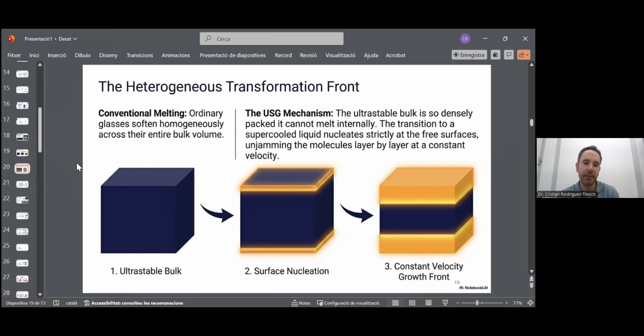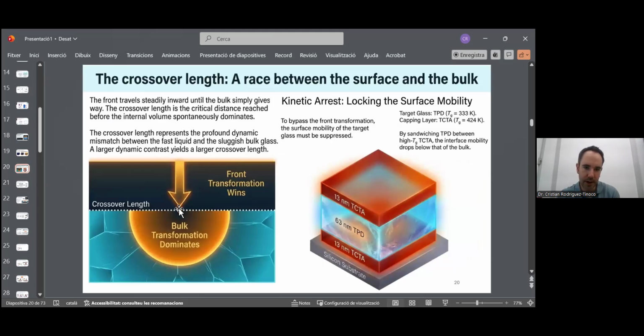What I want to say is that this front, so the liquid layer starts here on the surface and propagates into the bulk, but eventually the bulk of the system will go into the liquid state as well. After some time, the mobility of the bulk has had some time, and then it will transform into the liquid state. So we can define a crossover length, which is the distance that this liquid front can travel before the bulk transformation dominates. Okay, so this is the crossover length.